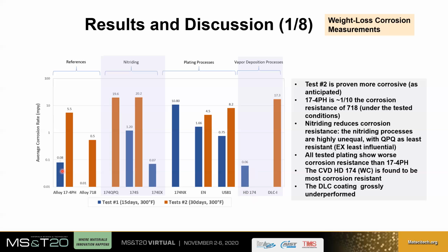the bare material. Okay. And finally, when we move towards the DLC coating, this is a very specific DLC from one vendor. It was selected to be thick, about 20 micrometers in thickness. And we can see that this particular DLC did not perform at all. The reported weight loss is very comparable to the plating. And we'll understand shortly why it is comparable to the plating.